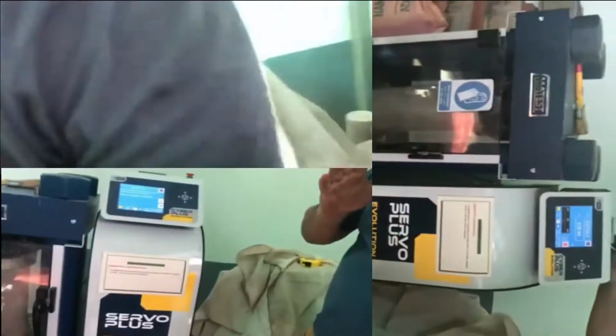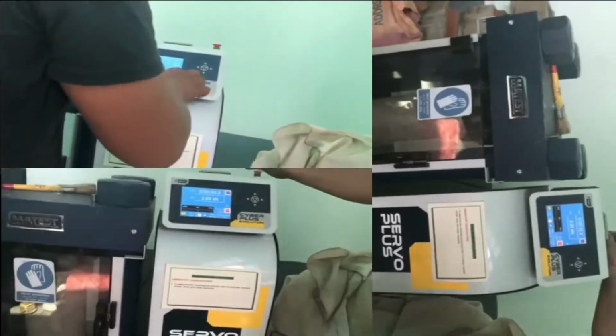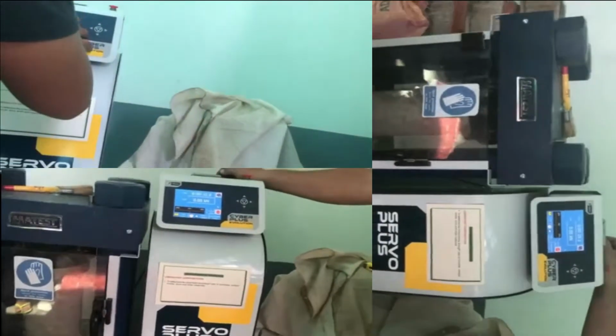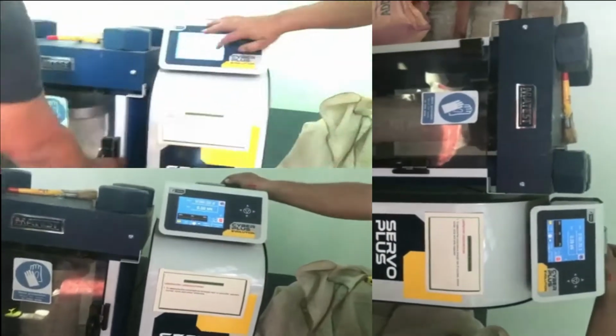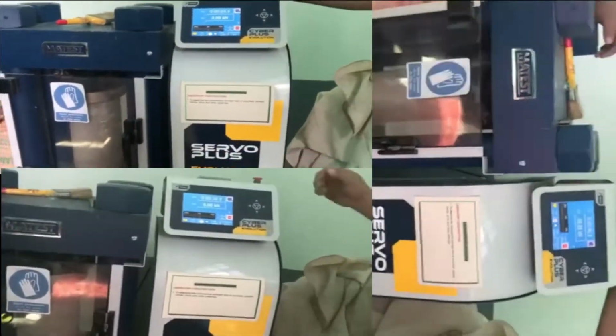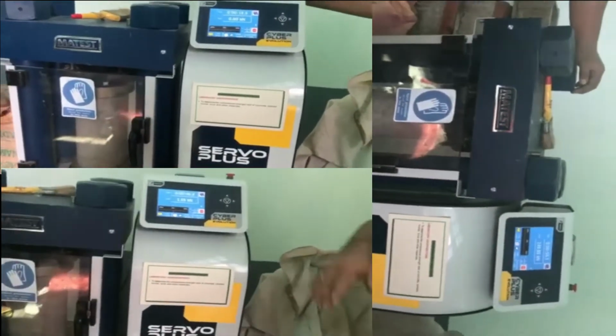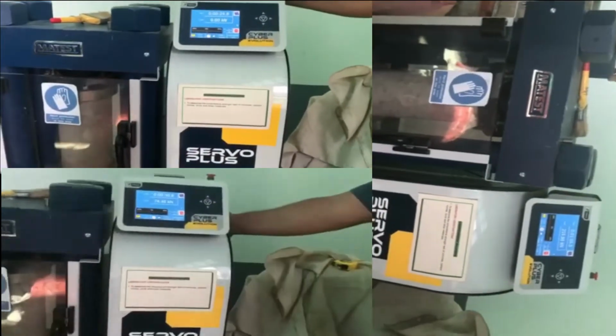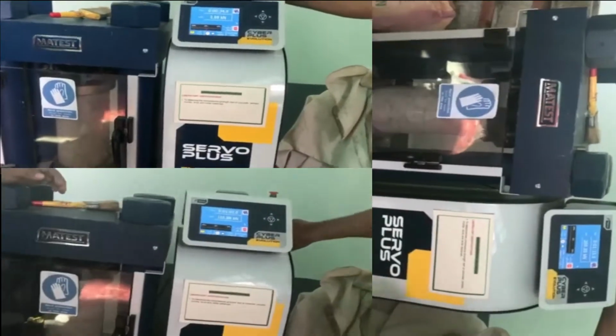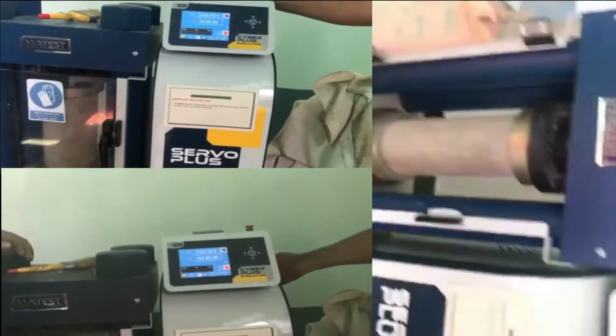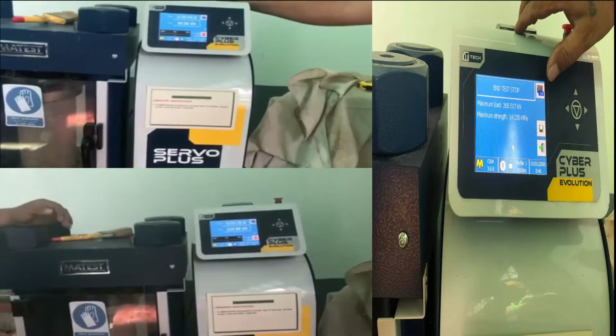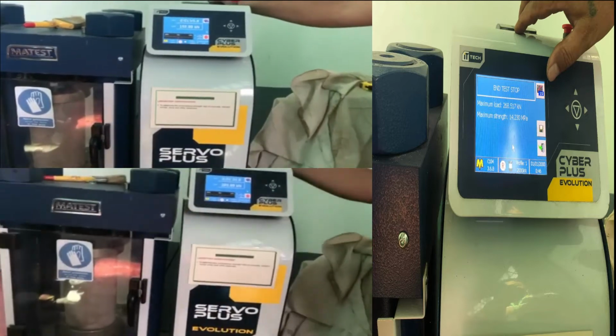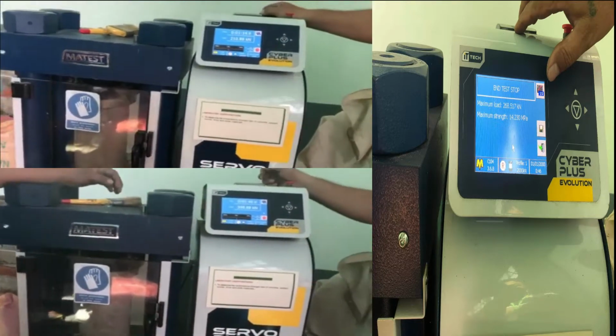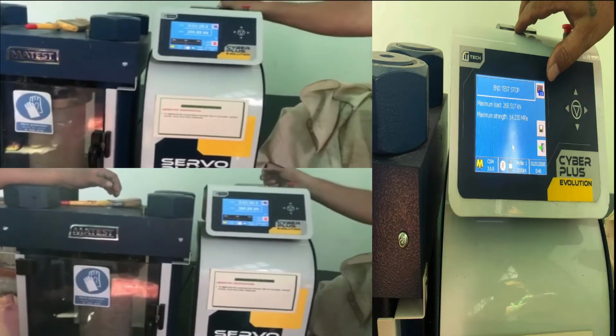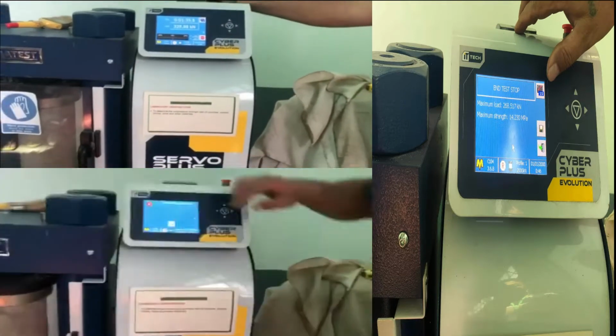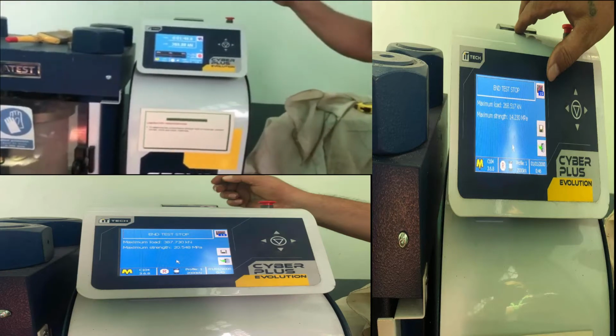The sample with water cement ratio 0.45 had a maximum strength of 23.693 megapascal with a maximum load of 447.070 kilonewton. Meanwhile, the 0.55 water cement ratio gained a maximum strength of 20.548 megapascal and a maximum load of 387.730 kilonewton. And the 0.65 sample had a maximum strength of 14.230 megapascal and a maximum load of 268.517 kilonewton.